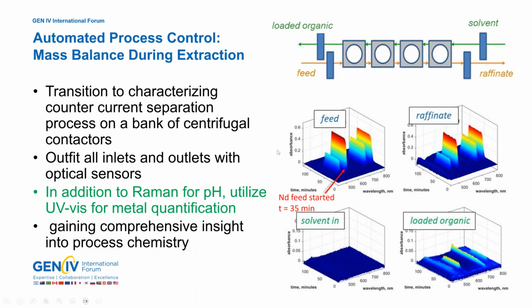As we can see, at the very beginning we start with no neodymium in the feed, but at 35 minutes into the experiment, we switched over to a feed that contained neodymium. We see an immediate increase in the bands related to neodymium across the UV-vis spectrum until we stopped the neodymium feed at 90 minutes into the experiment, and then that band dropped back down again and continued on to its solvent. In the raffinate position, as soon as we added the neodymium to the feed, we had neodymium reporting out to the raffinate position, and also down in the loaded organic, we could see the neodymium bands coming in from the extraction of neodymium into the organic phase.